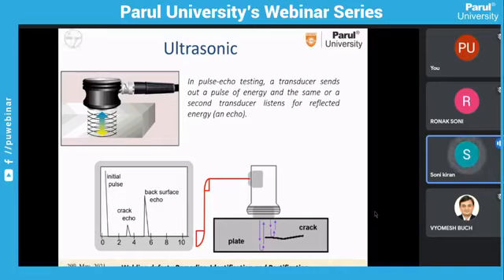So in a display you can see that the initial echo is there, the back wall surface echo is there, and in between the cracked echo is there. So based on the scale, in this display there is a scale, if the base metal thickness is 6 mm or 5 mm, then my defect is at around 3 mm. This is how we can identify the depth of the defect, and by skill of the operator you can also judge what morphology of defect, whether it is cracks, slag, that he can identify. But here he can pick the indication with the depth.